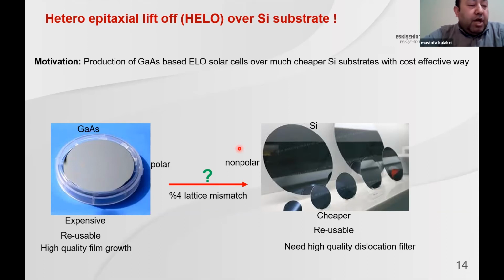Here, we are looking to decrease the substrate cost much more over conventional ELO cells. So we conducted research on heteroepitaxy over silicon substrate for the first time. I am not putting all details here due to patent concerns, and also this is the first time it is announced to anybody here. So instead of a gallium arsenide template, we use much cheaper silicon. When you compare with gallium arsenide at silicon price, the cost increases up to 1,000 times when you reach the 8-inch full substrate size. Of course, gallium arsenide technology is also now at 8-inch, but it is not matured yet, at very high prices.